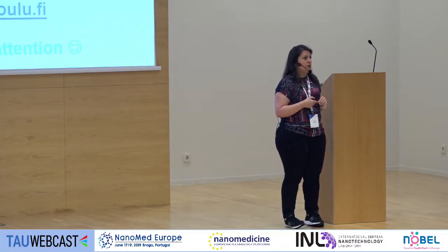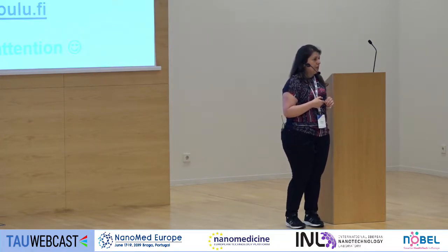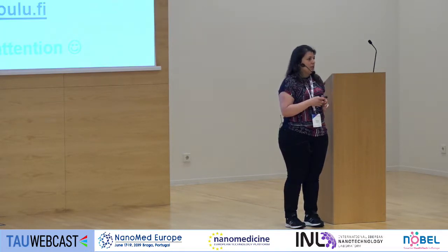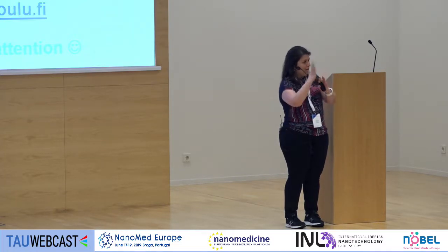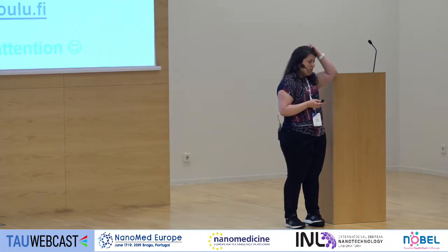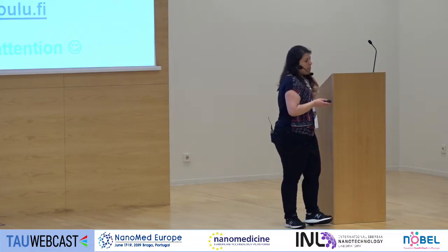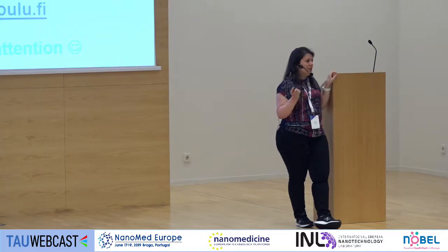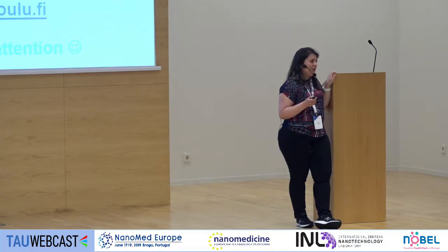The pillars have a Young's modulus of about 8 megapascal, and we have done finite element analysis of how much force you apply and how much they bend. We have some studies ongoing at the moment. What is really interesting is that the cells sit on top, not on the laterals. Yes, we were very surprised by that.